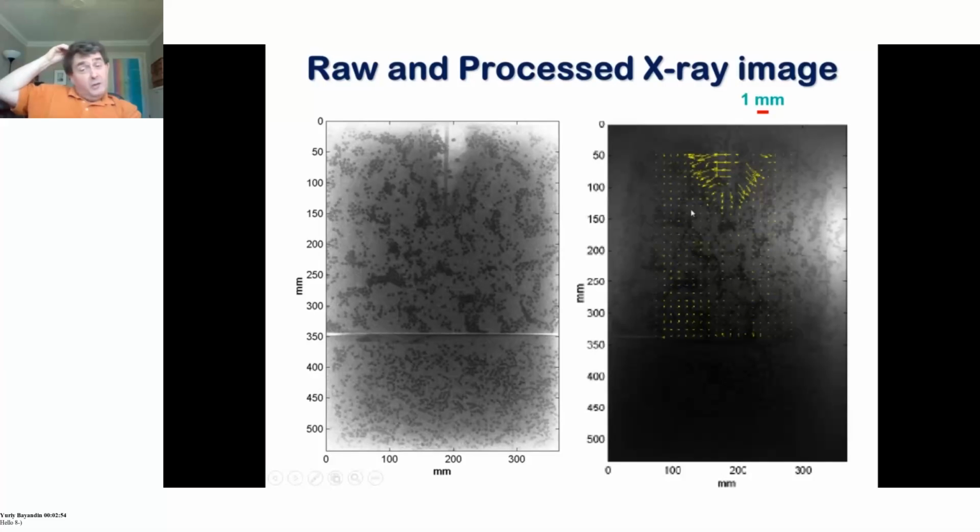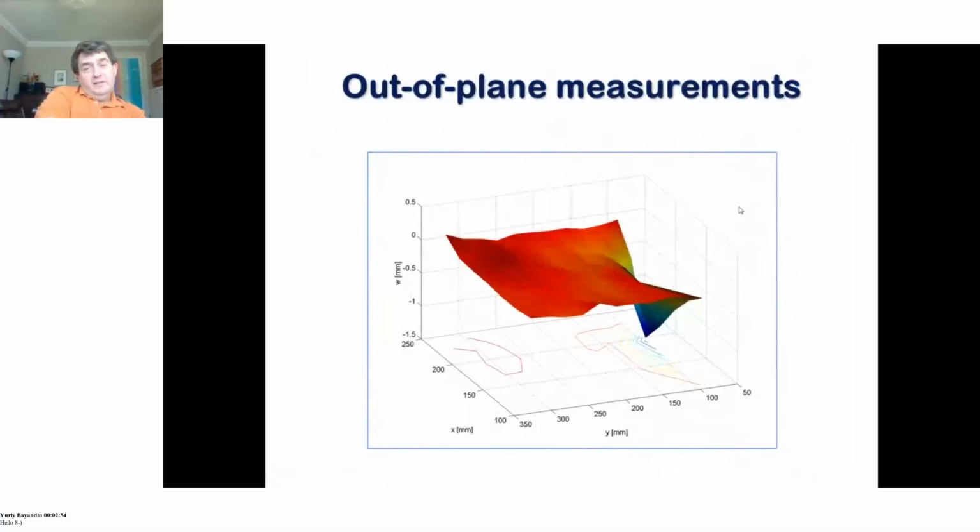It's supersonic with respect to the sound speed in the material. So that's why you've got this nice little cone of displacement. That's just 2D. But if we do the full 3D analysis, this is the shape. This is the entry point into the sample. This is the shape of the lead layer. And please notice, we're now talking an accuracy where we're going sub-millimeter.